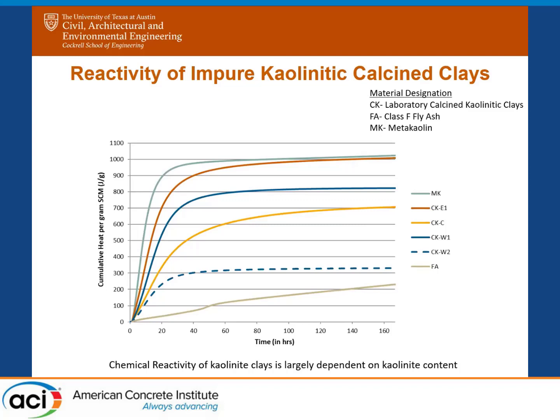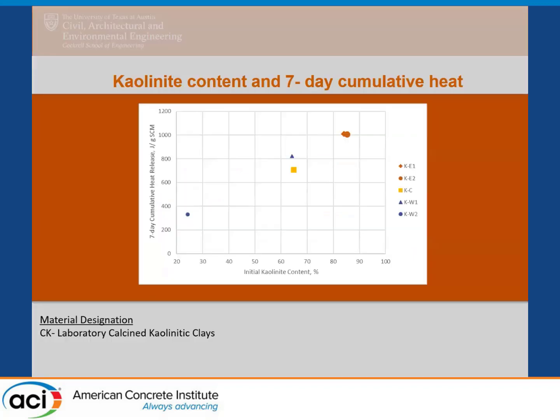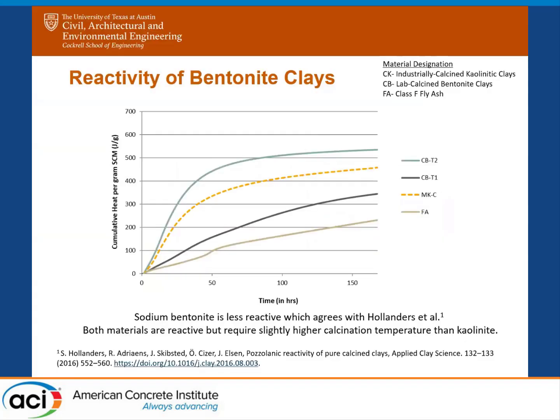So that has a much higher reactivity than the 24% kaolinite content down in CKW2, which is expected. And the CKC and CKW1 are those 65%, so they're right in the moderate range. And that's just to show this kaolinite content again. It's largely dependent on the heat. The heats are largely dependent on initial kaolinite content, which is expected. So we definitely are seeing that trend.